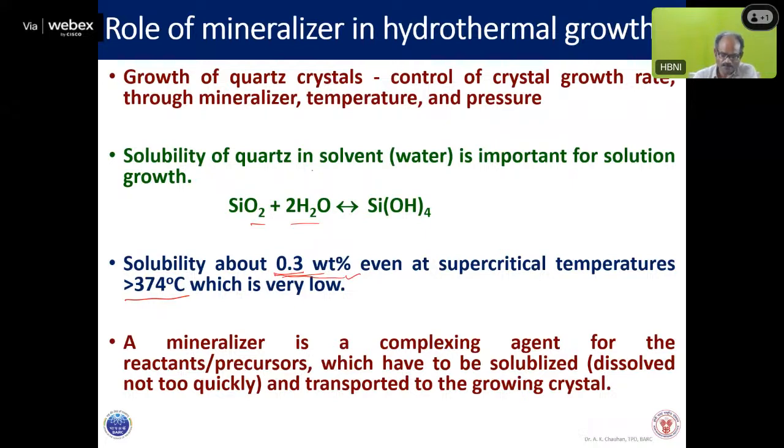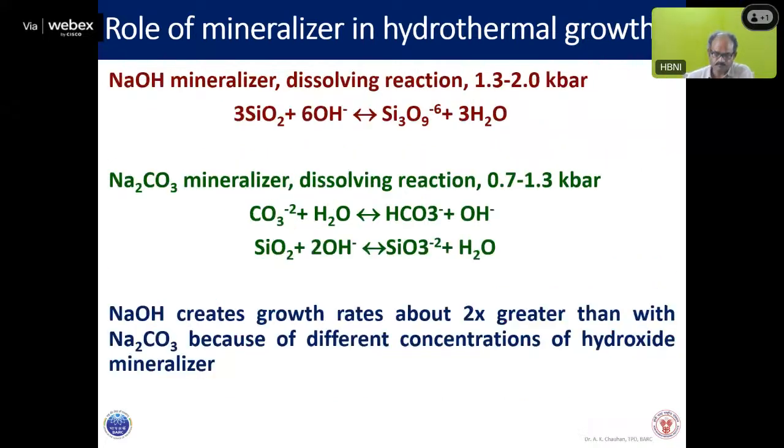And there is another thing which we can use, the mineralizer. What is a mineralizer? It's a complexing agent which solubilizes and transports this to the growing crystal. There are two mineralizers in the case of quartz. One is sodium hydroxide, another is sodium carbonate.